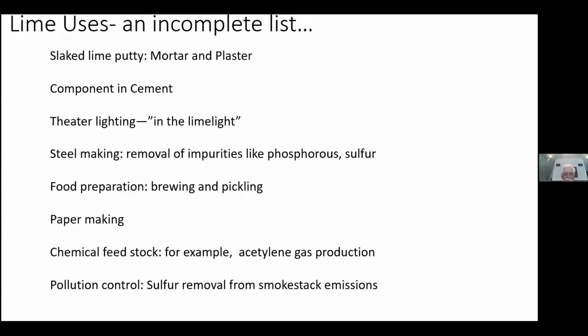Lime's also used in steel making. It can remove impurities from molten steel like phosphorus and sulfur. It's a very caustic material, and so it's also used in brewing and pickling. It's used in paper making. It's used as a chemical feedstock to produce all kinds of materials like, for example, acetylene gas. Pollution control, the sulfur removal that takes place in smokestacks, a lot of that has to do with recombining the sulfur with calcium oxide to produce a calcium sulfate to remove the sulfur from those gases.